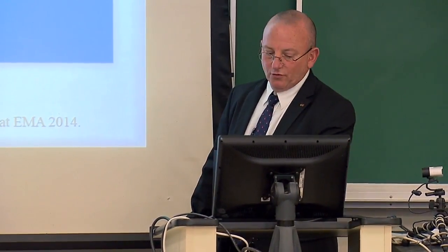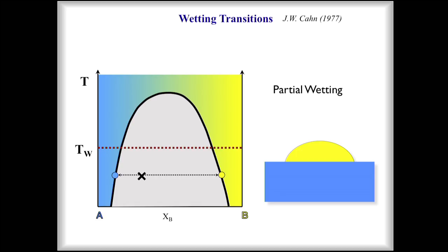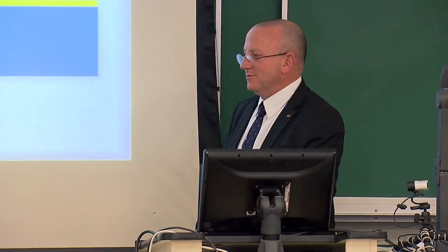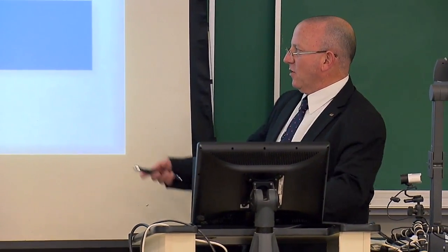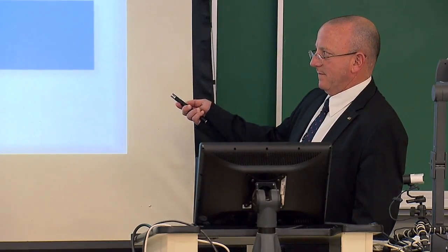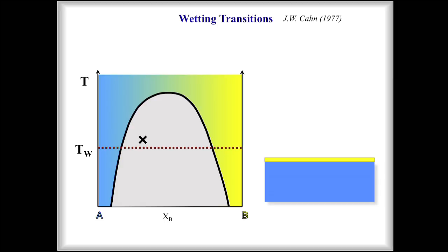What Cahn said, proved, and experimentally proved, is that if there is this critical temperature, and we cross it, there will be a change, and we'll go from a finite contact angle to a contact angle of zero, a wetting. Now, if we move from the left to the right, and this is important for the difference between adsorption and wetting, which is not the same, all we're going to get is a thicker film, right? This is wetting, a thicker film.